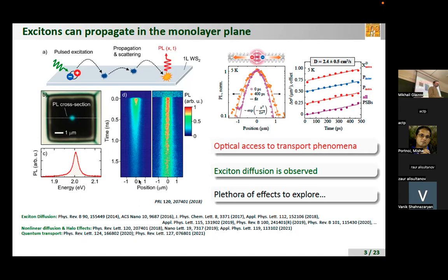It is very important, indeed. Bright excitons have a lifetime of several picoseconds. So even if you take into account all the states beyond the radiative cone, it would be, I don't know, 10, 20 picoseconds for reasonable temperature. So in fact, what people observe here is the dark exciton diffusion. In this case, lifetimes are long, but there are different mechanisms by which dark excitons can be converted to bright: small violation of symmetry and change of the selection rules.